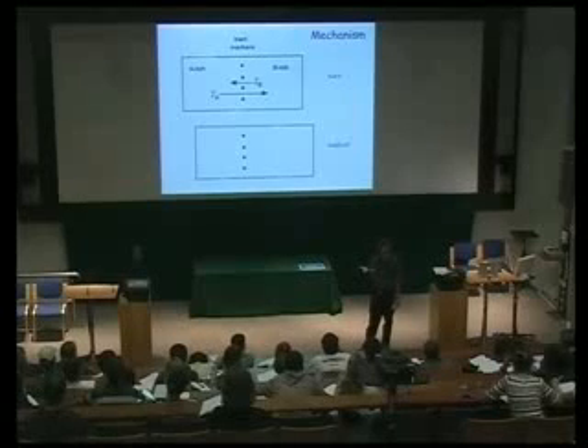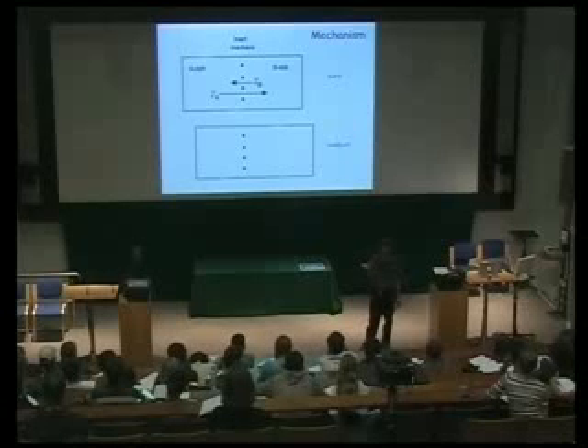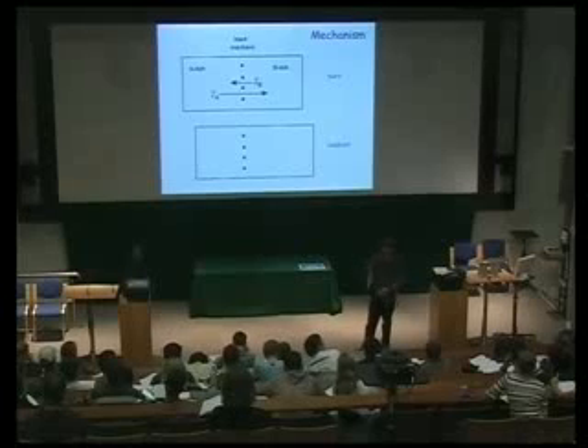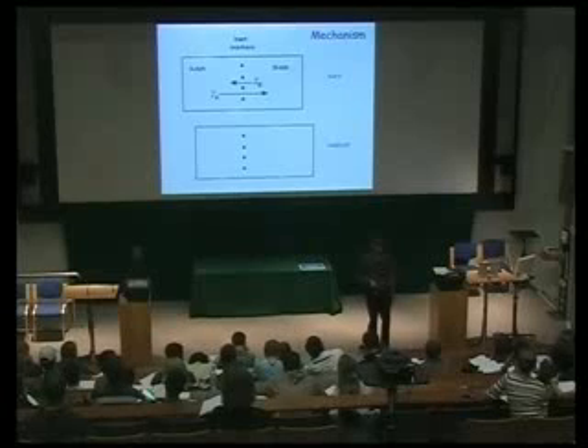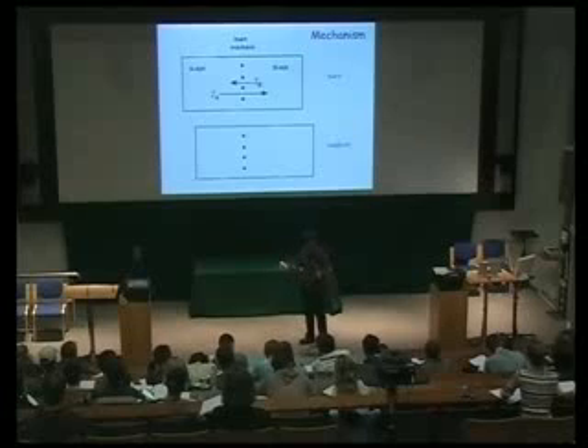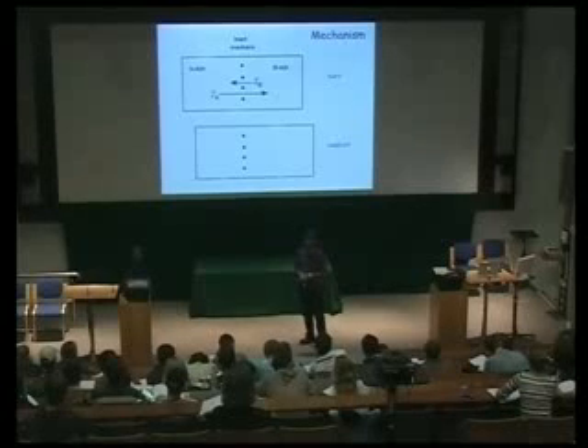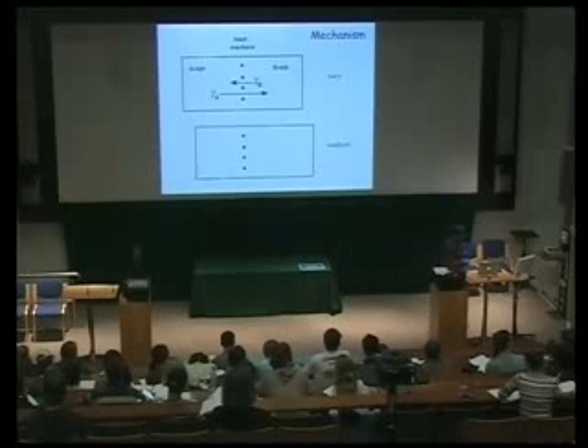Now, this can only happen if it's a vacancy mechanism, because if it is a place exchange, then you must have equal fluxes in both directions. If you're swapping a copper atom with zinc, then the copper atom moves that way and the zinc atom moves that way, and you cannot get a net translation. So this is a unique and very, very elegant experiment which proves beyond any doubt that diffusion happens by a vacancy mechanism in the vast majority of crystalline substances.